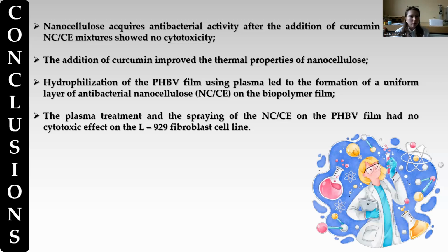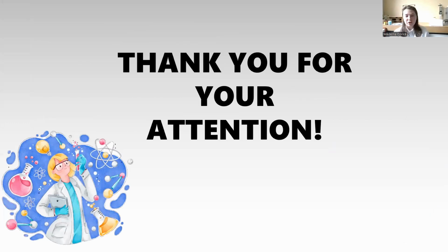Following our work, we can conclude that nanocellulose acquires antibacterial activity after the addition of curcumin, and the nanocellulose and curcumin extraction mixture show no cytotoxicity, and the addition of curcumin improves the thermal properties of nanocellulose. The hydrophilization of the PHBV film using plasma led to the formation of a hydrophilic layer of antibacterial nanocellulose on the biopolymer film. While the plasma treatment and the spraying of the nanocellulose with the addition of curcumin on the PHBV films show no cytotoxic effect on the L929 fibroblast cell line. Thank you for your attention.